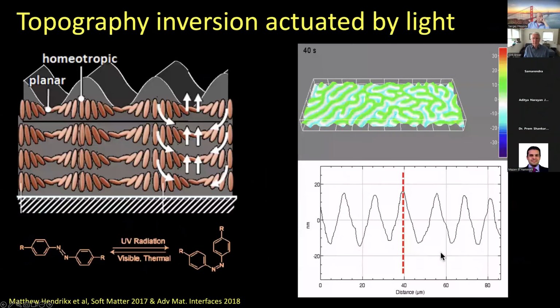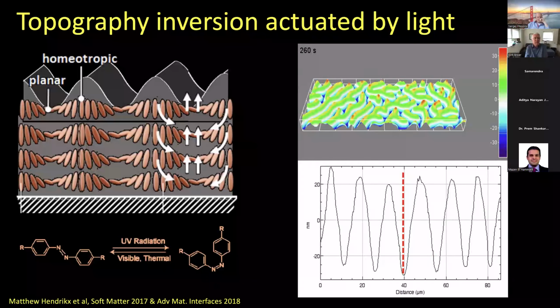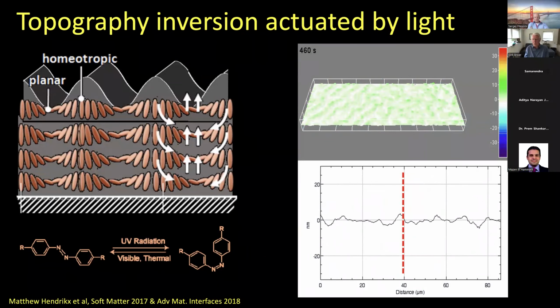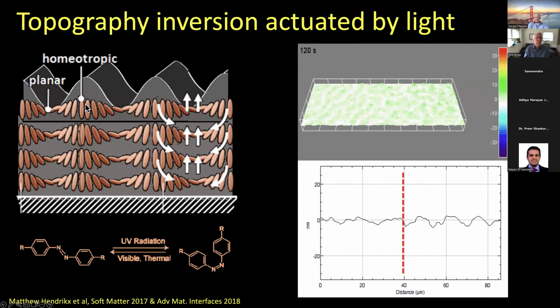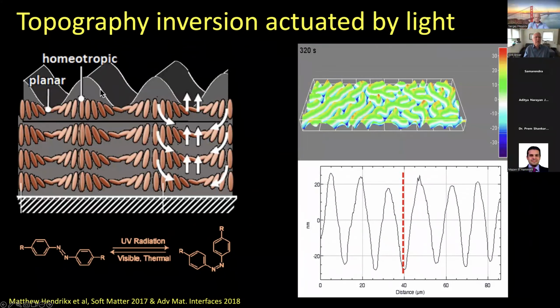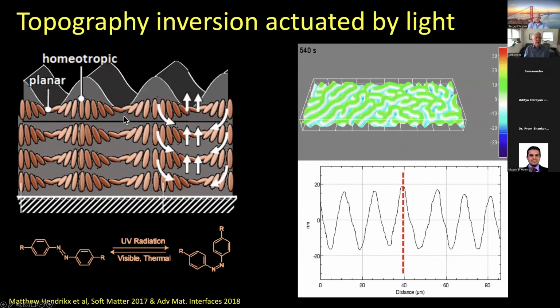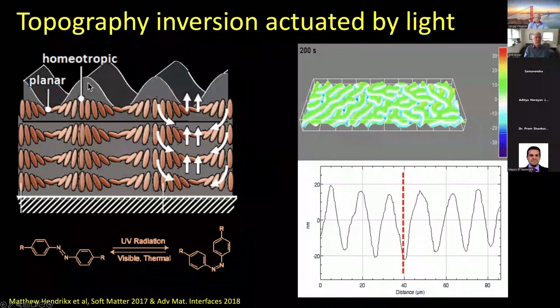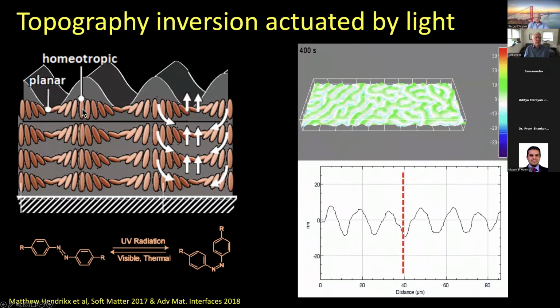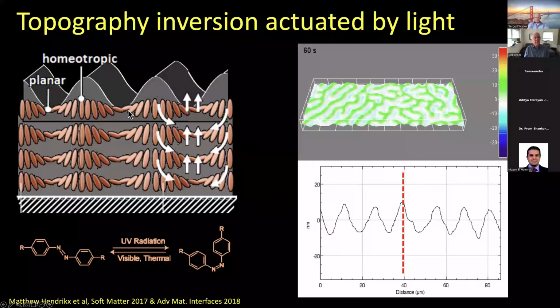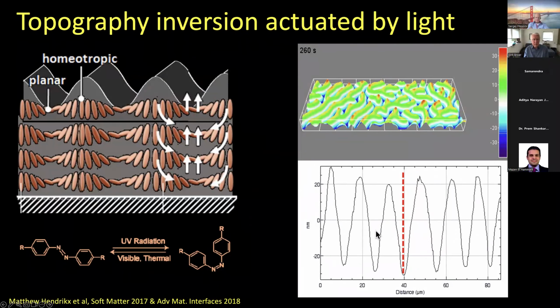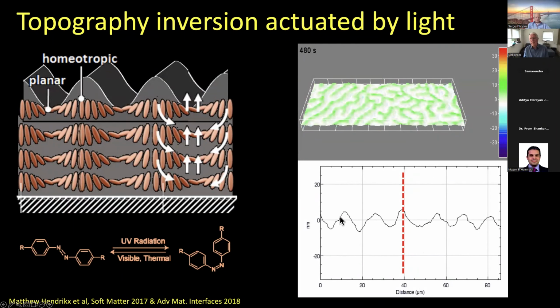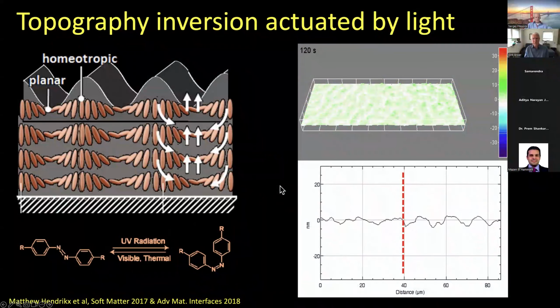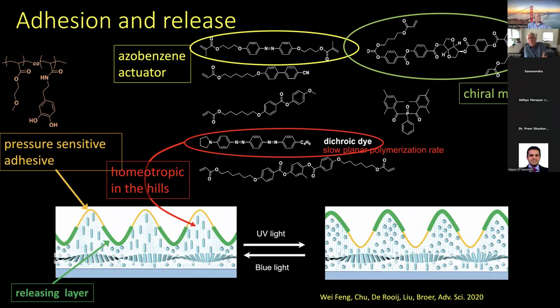And now you can start playing with this. You can basically start inverting this system. So if this is the case, homeotropic areas are higher, then you start actuating. This will shrink, this will actuate, and you go from one state where the hills become valleys, and the valleys become hills. So you're basically inverting the surfaces. And this can, for instance, be used to play with the adhesion properties of the surfaces.